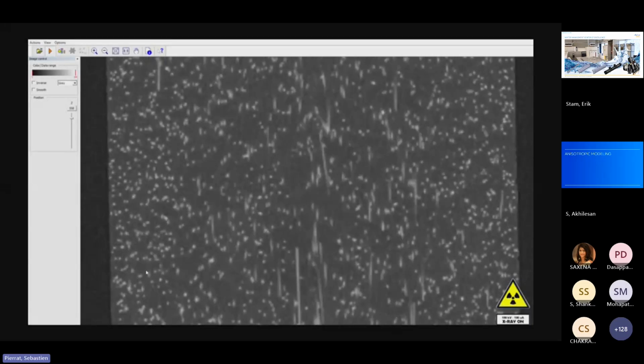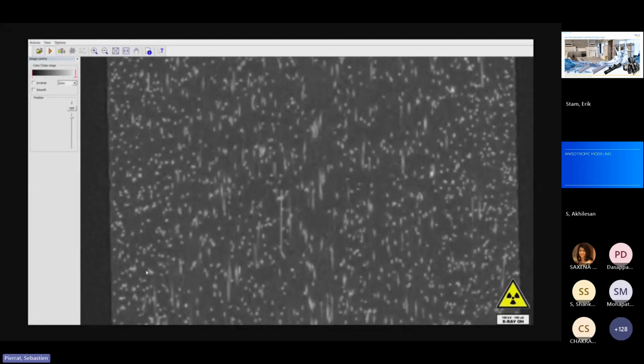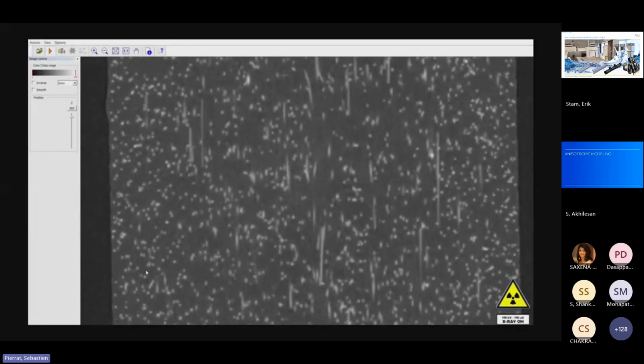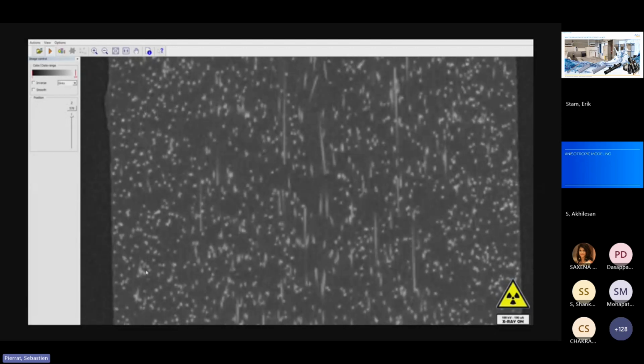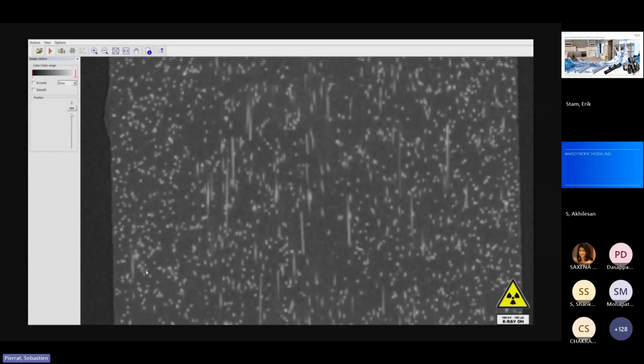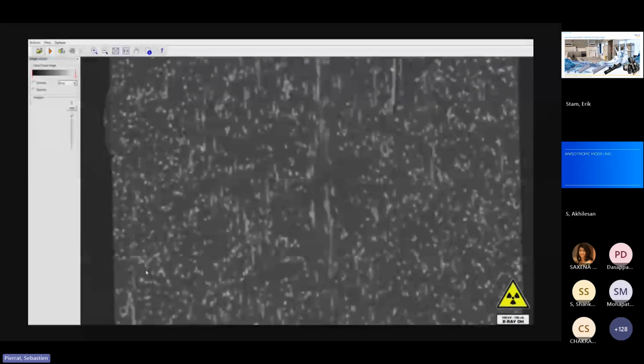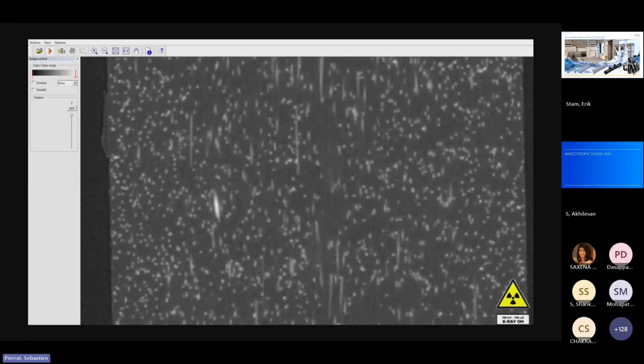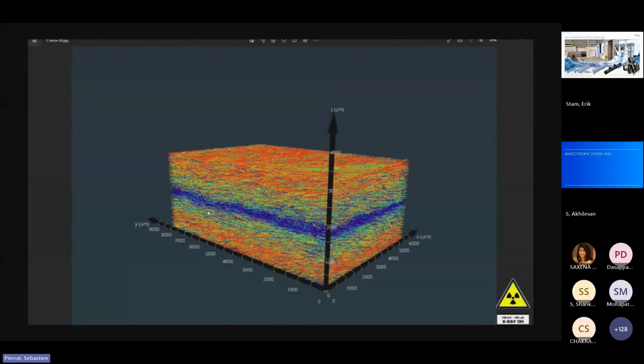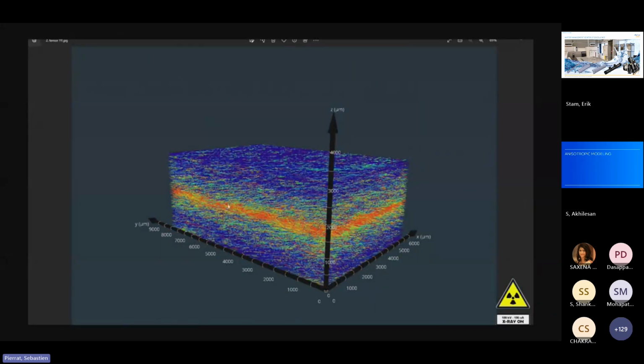Using a 3D image analysis software, I can detect the individual fibers and track the center line of each of the fibers along the length, as well as measure the local orientation of the fiber. This can be represented in 3D in color-coded images where red color shows strong orientation, blue color low orientation. We can clearly see on this image that the fibers are strongly oriented along the flow close to the surface, whereas they are oriented perpendicular or more perpendicular to the flow in the core of the material.